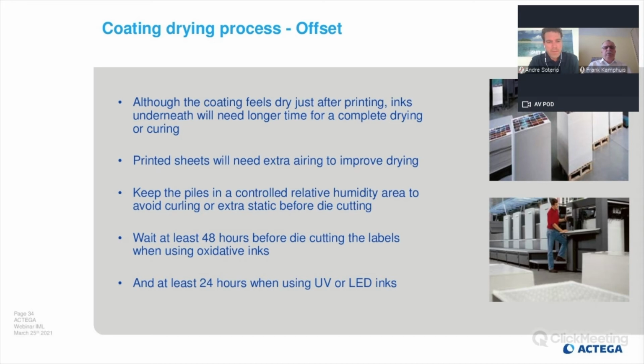If you're using UV inks or LED inks, even if the ink is dry immediately, please keep in mind that you can have some humidity inside, and that could also cause some problems. So we recommend to wait 24 hours.